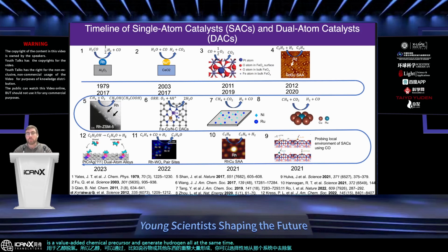So there could be opportunities here looking at a silver nanoparticle, so this is all done kind of surface science approach on extended single crystals. But if you had a silver nanoparticle with a plasmon resonance and you could dope in platinum and chromium and use ethanol from a bio-derived source, there could be opportunities for hydrogen generation while at the same time generating some precursors or some output products that have some value that aren't all the way down to the kinetically and thermodynamically favored process of CO2. So there could be a lot of interesting areas in that.